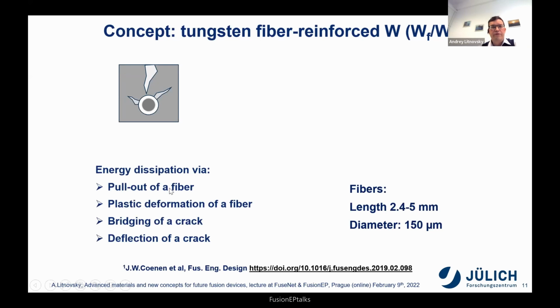Looking at the performance, one of the perfect examples is so-called tungsten-fiber-reinforced tungsten. It is similar to carbon fibers. We are introducing small wire-like fibers into the tungsten matrix. The idea here is to make the energy dissipate. The energy which would rather go to crack formation and destruction of the material will be dissipated by pulling out of the fiber, plastic deformation, bridging the crack, or deflection of the crack.